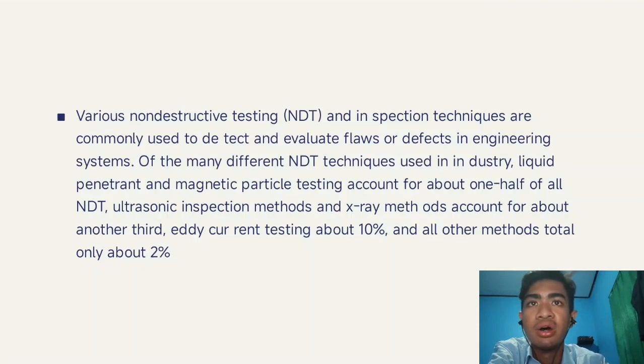A color dye or a fluorescence compound is usually added to the penetrant liquid. Depending on the amount of penetrant that seeps to the developer, the crack width can appear up to 100 times larger than the actual size. The equipment required for liquid penetrant inspection is usually simpler and less expensive than that used for other NDT methods. The inspection can be performed at many different stages in the production of a component, as well as after the component is placed in service.